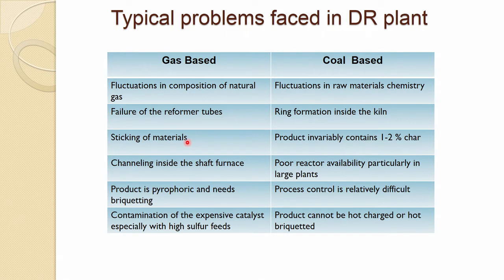Sticking of materials is one of the major problems, especially when withdrawing material after reduction if some low melting gangue has formed. Sticking problems may occur and are quite prevalent. Channeling inside the shaft furnace, similar to the blast furnace, is another issue. The product is pyrophoric and needs briquetting.